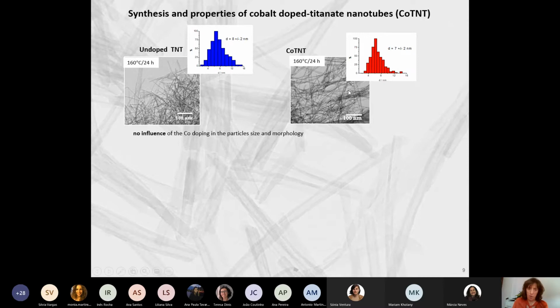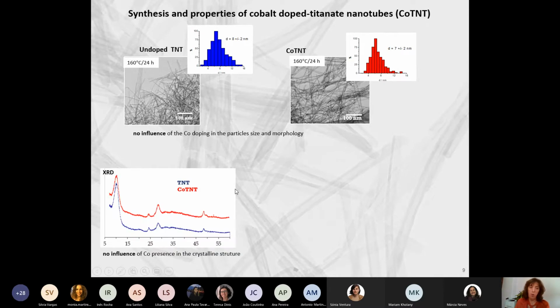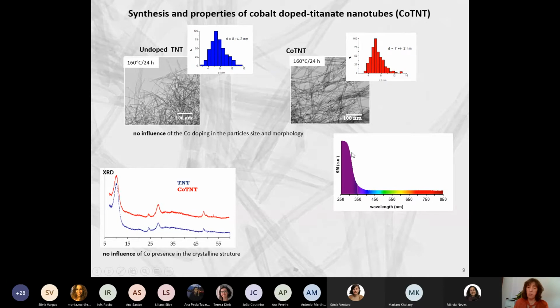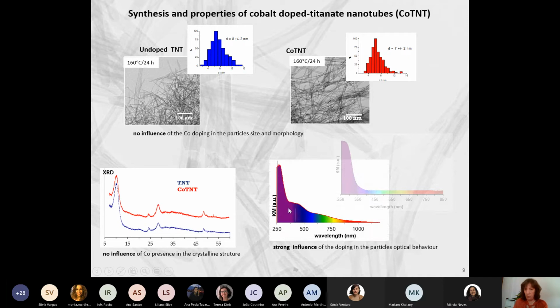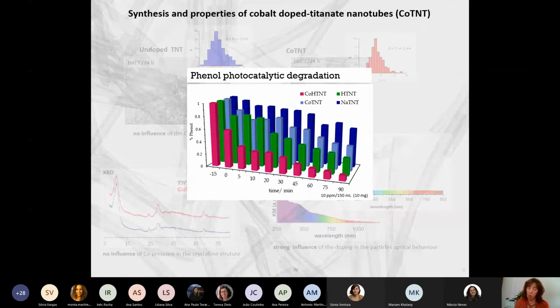As you can see here, we have more or less the same dimensions of our particles. If we look at the XRD, we have no changes in the structure. But of course, if we look at the optical spectrum, we can see that when we have the incorporation of cobalt as dopant, we start to have absorption in the visible. Just to show you how this can be important when we talk about photocatalytic degradation, we can look at this picture, and as you can see, when we replace the sodium by the proton, we have an increase in the performance of the photocatalyst. Also, if we use a doping system, in this case with cobalt.